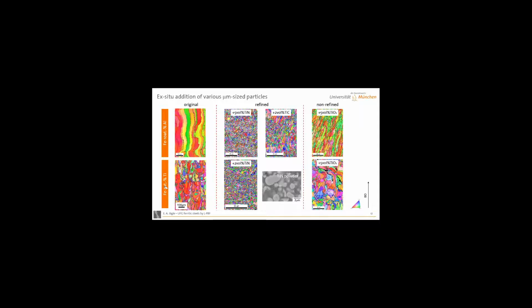And just to add to the discussion that we just started about whether the yttria dissolves or not, this is the microstructure of the material after L-PBF processing. Here at the bottom, you see that most of our TiN particles are 1 micron and above. And afterwards, none of them are even close to 1 micron. And TiN is a material that has a melting point, I just checked Wikipedia just before my presentation, of nearly 3000 degrees C. So I would say apparently in the melt pool, there is enough thermal energy to somehow make these TiN particles go from several micron to maybe 100 nanometer.